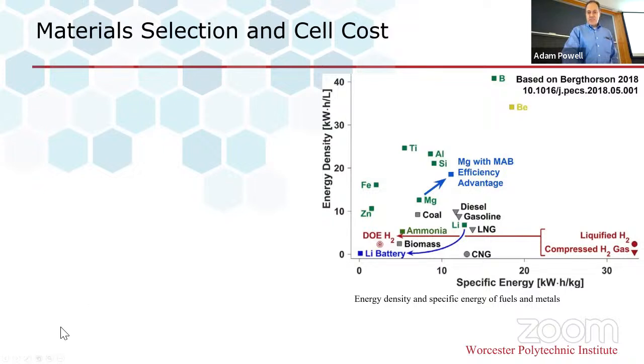In terms of the material selection, as mentioned, magnesium has not only a high energy density. Aluminum and silicon beat it, but silicon halides are gases that would come right out of it. So that's not an option. Aluminum could be an option. However, its oxide scale is very stable, very low solubility. So you get passivation of the aluminum the way that you get passivation of magnesium in a magnesium air battery. Magnesium is a logical choice for these reasons.